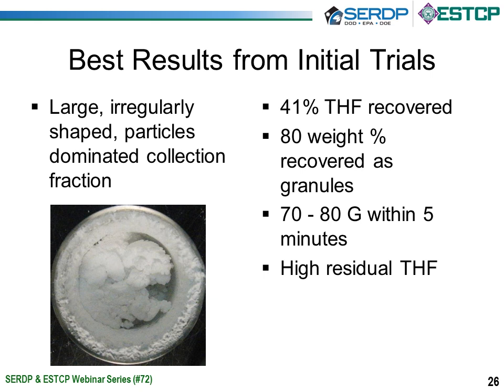In this best run, we used 70 to 80 Gs within 5 minutes, and we noticed that there was still high residual THF in the granule formation.